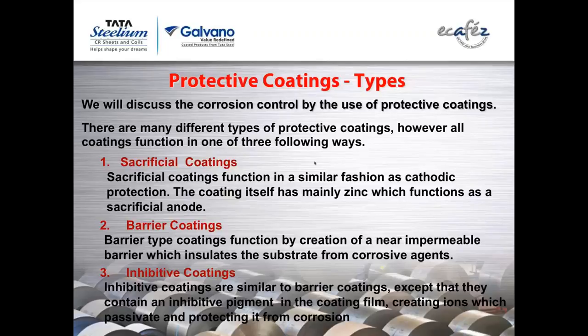Third, what we call inhibitive coating. Now, these inhibitive coatings are similar to barrier coatings, except they contain some inhibitive pigments in the coating film. Certain pigments like zinc chromate and all are now banned under RoHS, and especially on exports you cannot use this. So these are replaced by pigments like zinc phosphate and all. So these inhibitive pigments are there in the coating film, and they will create ions which will passivate when they come into contact with humidity or moisture, so that when they passivate, they will protect the film from corrosion.